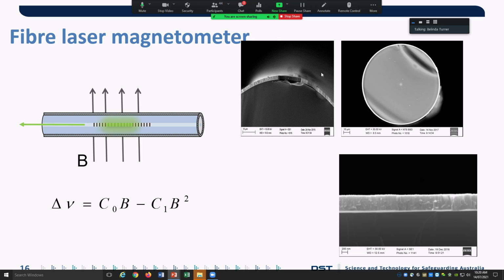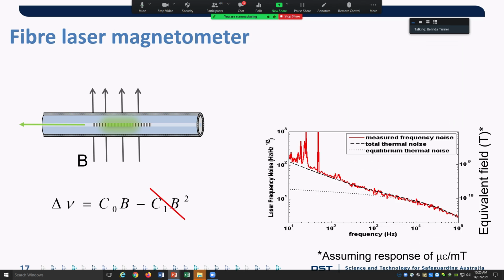Terfenol-D coating optical fibre, and you can see the nice thin layers of around about a micron thick. So I did some calculations based on what was published in the literature for the amount of strain you get on the amount of wavelength shift you get in conventional Bragg grating sensors.